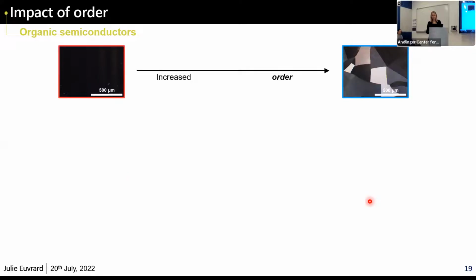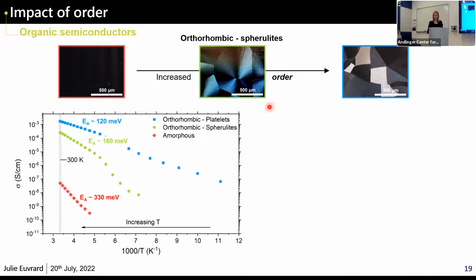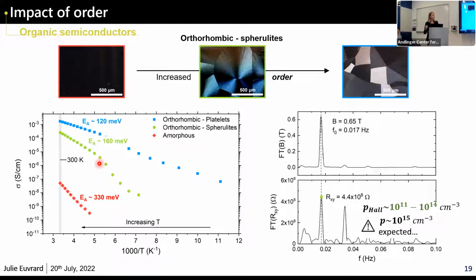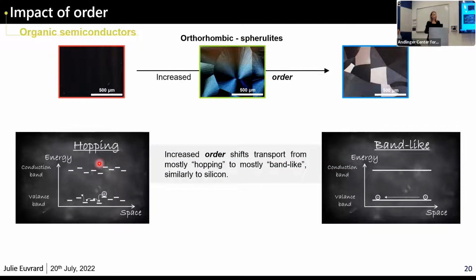Now, what's happening in between? I said you can induce disorder inside the grain. And interestingly, when we look at the experimental results, we obtain something in between. We have a conductivity that is in between those two extreme cases, an evolution with temperature that is also in between, and the density we get from Hall effect is also between what we expect and the most extreme case of amorphous. So what we conclude from that is that when you go from highly disordered to highly ordered, you're going from one transport mechanism, which is mostly hopping, which is inefficient, to another extreme where the transport mechanism is very different, band-like, and much more efficient, but you're going in a very continuous way. You're not going from one to the other suddenly, you're going in a continuous manner.